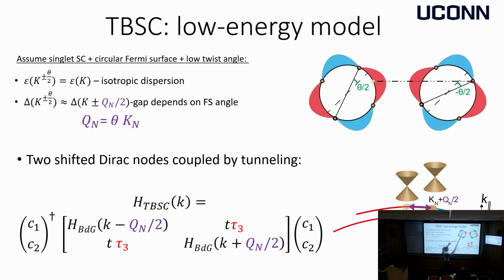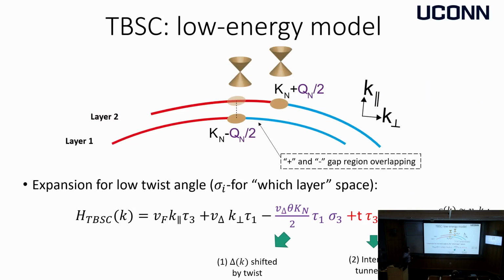is that if we start with a circular Fermi surface, the rotation doesn't do anything to the Fermi surface, but the rotation clearly changes the position of the zeros in the superconducting gap. And at low twists, you can essentially substitute a rotation by a shift. And what happens is that you just take 2 instances of the same Hamiltonian for the Dirac cone, and you shift it in opposite directions in 2 layers, like θ/2 and minus θ/2. And you allow for the tunneling, just single electron tunneling, nothing fancy between the 2 layers. So that allows for a very simple form for the Hamiltonian, which you can solve and understand basically everything about it.